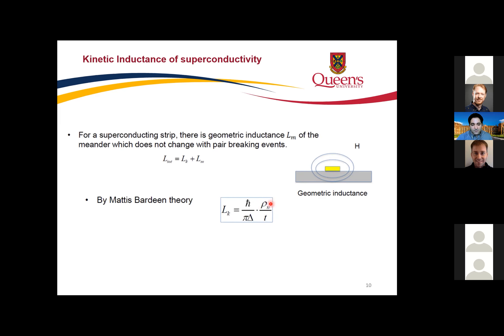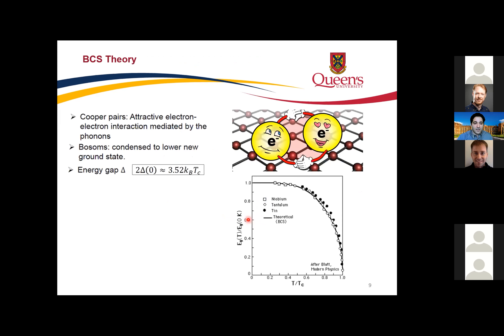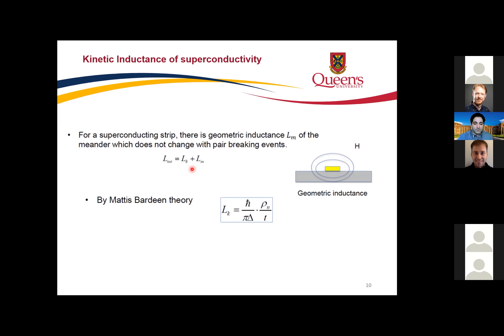The material choice is important. We also aim to lower the critical temperature below 1 K by combining materials, since the energy gap is related to Tc. We aim to decrease thickness, but there are limits: for aluminum the minimum is about 20 nm, and for titanium nitride about 40 nm. The main aim is therefore to decrease the critical temperature through material engineering.